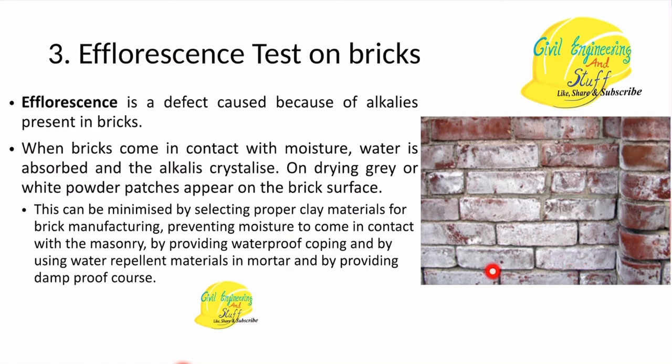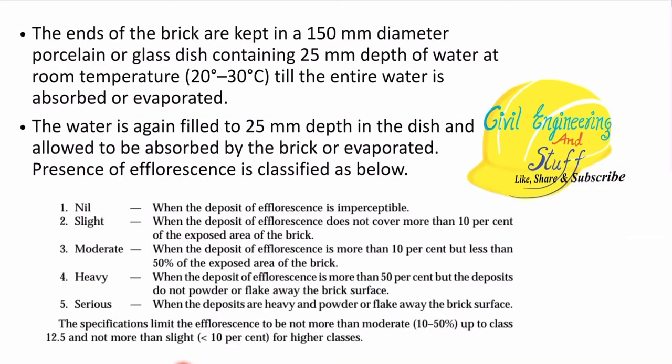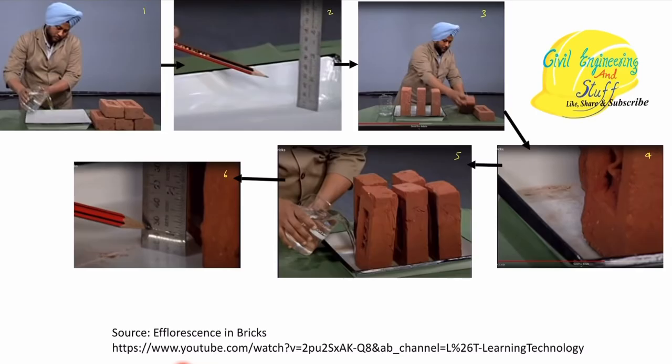And to minimize this efflorescence, we have to properly select the clay that is used for the construction of the bricks. So basically in this test, we take the brick samples. The brick samples should be dry. We take water, 25 mm depth of water is filled in the tray.